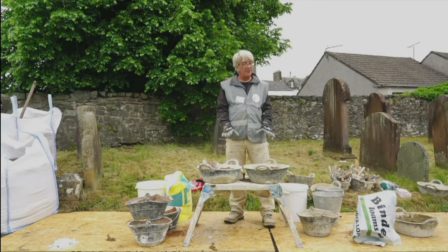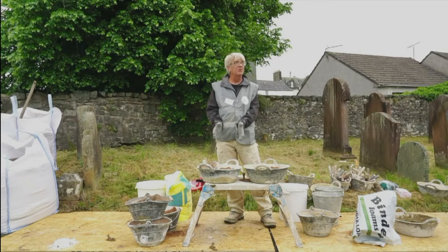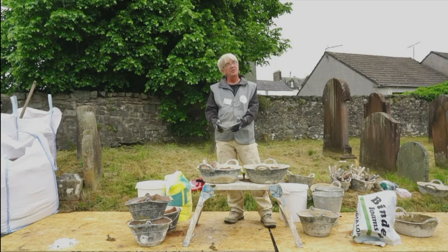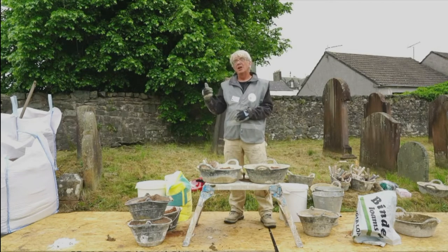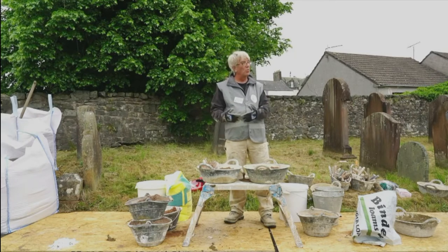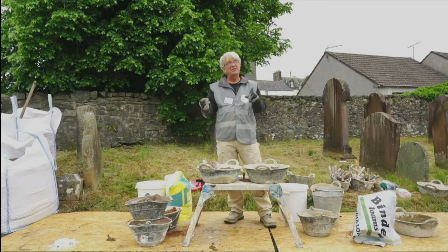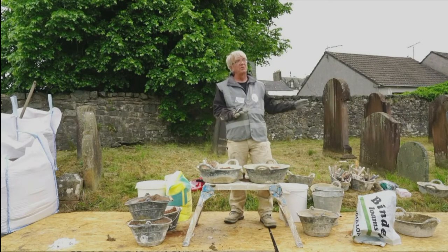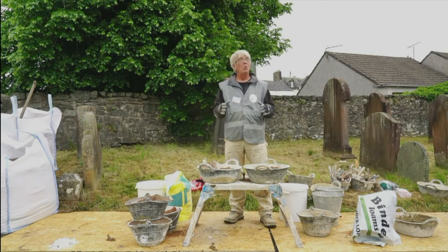The other way, the ordinary method, is to wet slake, I suppose we could call it. So I want to make this through to a mortar in one go, far more efficient, less handling, and I want to use it straight away. So I can put more water in the first instance, two and a half parts of water, all in one go, bank it over, and that will slake to a combination of some powder, but otherwise paste. They would call it paste, not lime putty, because that's a very specific material, which we didn't understand. Then you mix the two together, and if you want to use it quickly, you would add the water you need to bring it to the water content you want according to what you're doing with it.